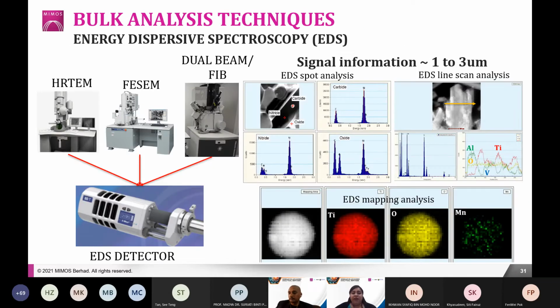So as I mentioned just now, the EDS detector is already attached to the high resolution TEM, FESEM and dual beam. All right. What are the information you need? For example, the EDS spot analysis. You need to know at that particular spot, what is the element present there? So you can use the EDS spot analysis. And then sometimes there are customers who want to know along the thin film, they have a few layers, right? So they use the line scan analysis, so we can give the line scan to show that this element is present at this particular layer.